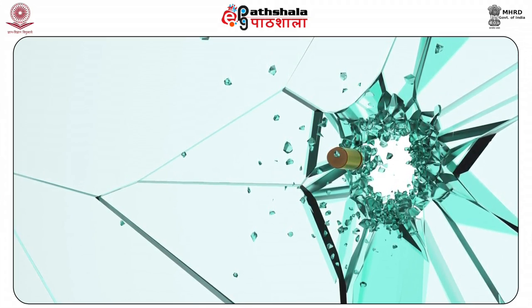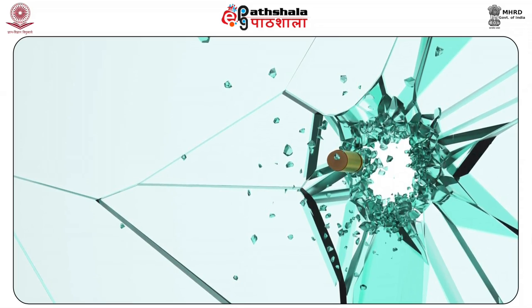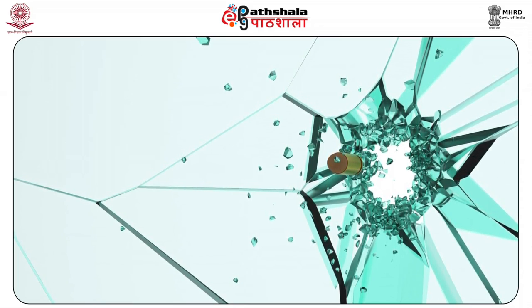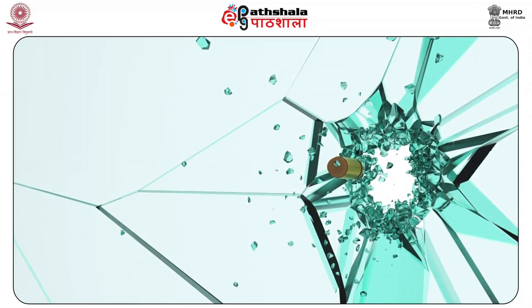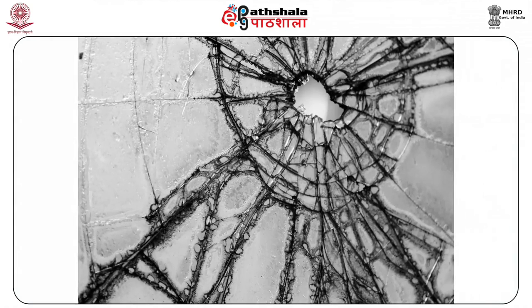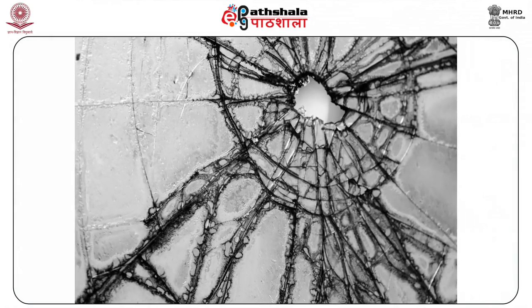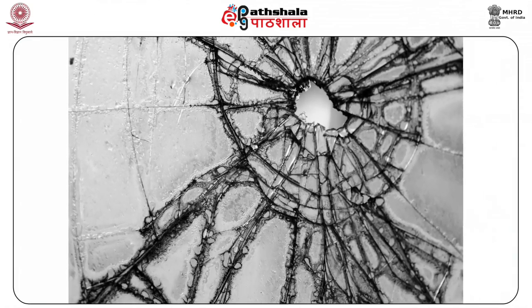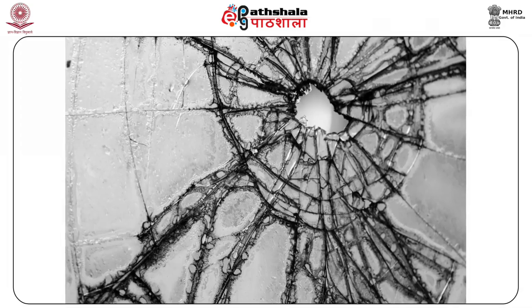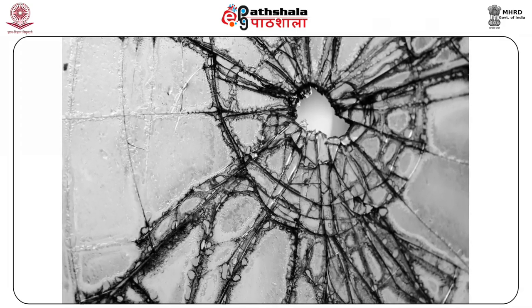These can be used to determine which hole was made first. A radial fracture in glass travels some distance, and if it meets another radial fracture that has been formed earlier, it will be stopped. Thus, if the fracture lines from one bullet hole are stopped by the fracture lines of another bullet hole, it may be concluded that the latter was made first.